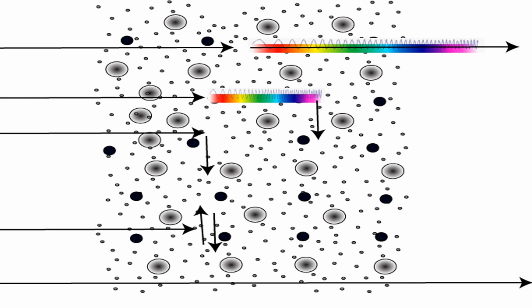And the advantage here is that it comes from a semiconductor material. It's not a phosphor, like in the conventional technology, and then you don't need rare earth metals. And when you combine these 2 broad spectra, it's a pure white light. There's no blue tone, like in the nitride-based LED. So this made a particular niche avenue for the LED. There are many things still to be resolved about that, but from a research point of view, it's an opportunity, and also from a technology point of view, if we can commercialize this once we have matured it.